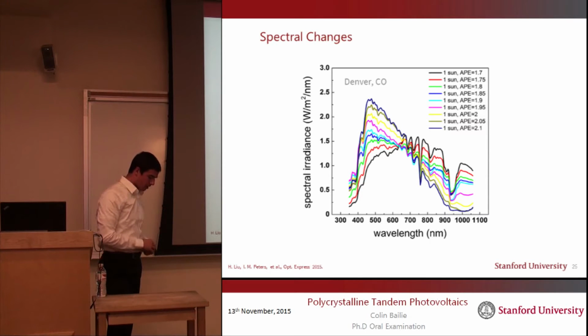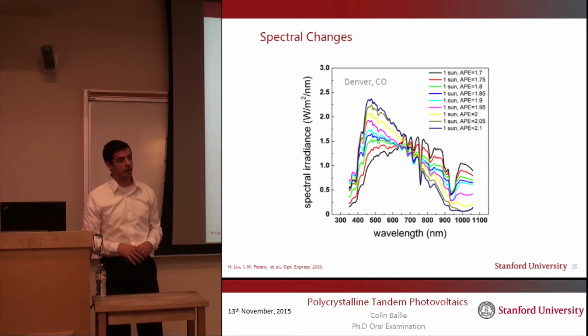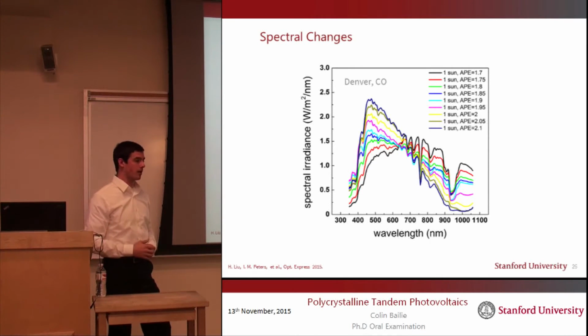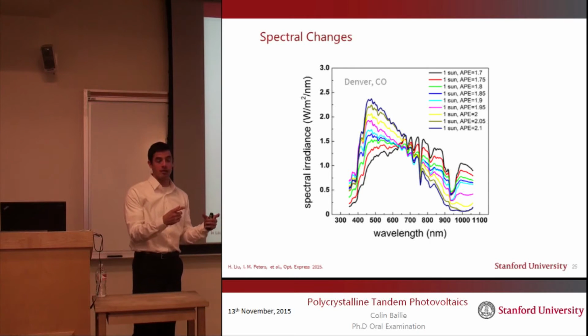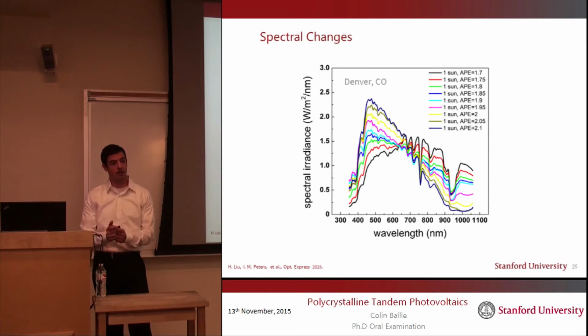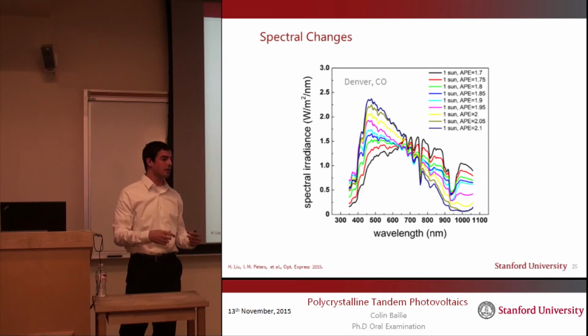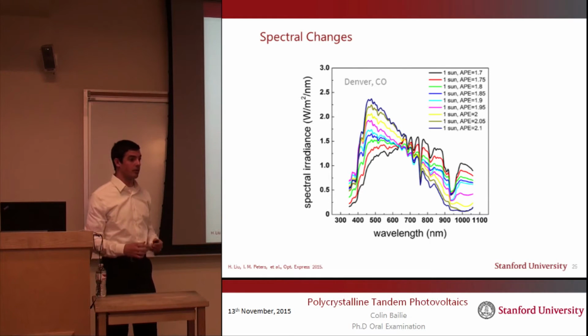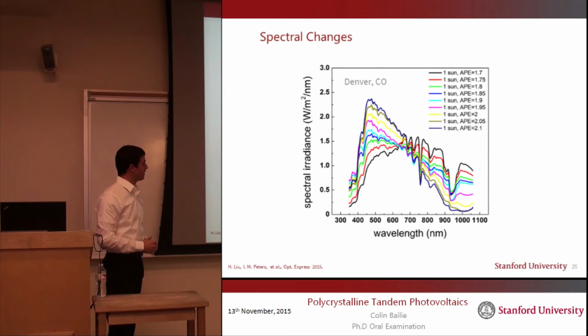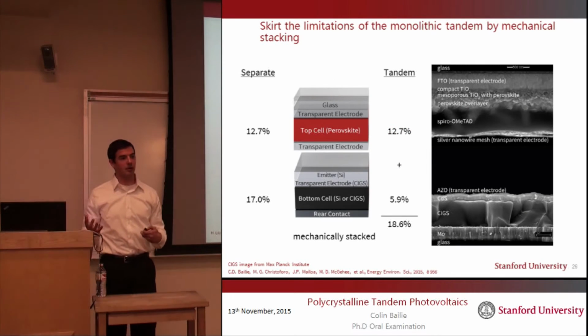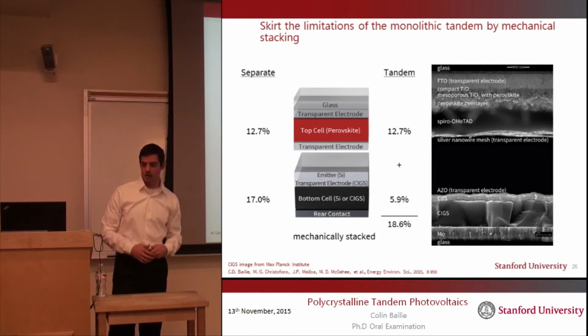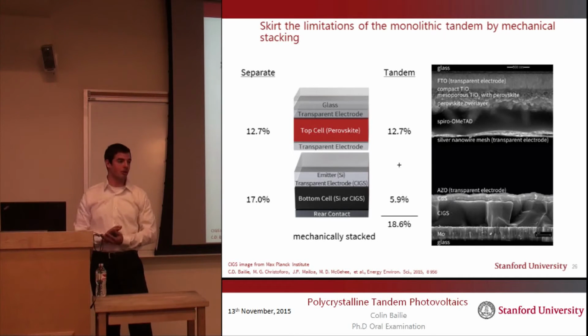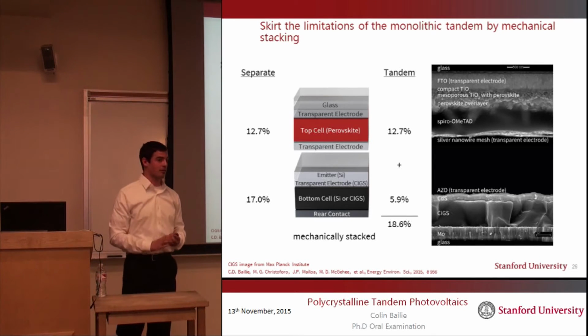And as was the problem a few slides ago with the monolithic tandem I showed you, whenever you have a current mismatch, then you're throwing away that power. So even though you may have made a 30% monolithic tandem solar cell in the lab, when you put it outside, it's highly unlikely to be anywhere near that number if you average it over the entire year. So with these Achilles heels in mind, how do we go about making our 30% tandem? And the answer is maybe you don't make it from monolithic tandems after all.